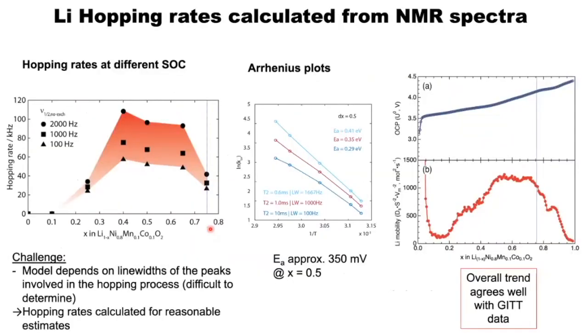So what does that mean? It means we can extract the hopping rates as a function of different states of charge. And what you can see is that when you remove more than 10% of the lithiums, you get a dramatic increase in the lithium mobility, reaching a maximum at some point between 0.4 and 0.6, while at 0.75, it's dropped off dramatically. We can extract activation barriers, the errors in the activation barriers coming from the assumptions in our